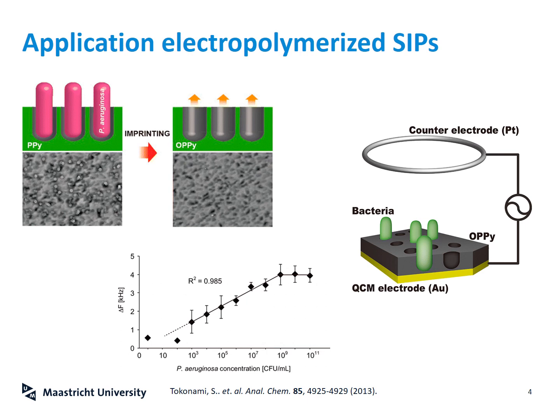You might also notice that the layer is about half the size of the bacteria, which is on purpose, because if you make the layer too shallow, then also the cavities will be too shallow and basically anything can bind to them. If you make the layer too big, then basically the polymer will be bigger and all bacteria will be buried and engulfed inside the polymer and you can't get them out and nothing can rebind to it anymore. So this just shows you one of the disadvantages: you really have to tweak your parameters to get exactly the desired thickness for your polymer layer here.